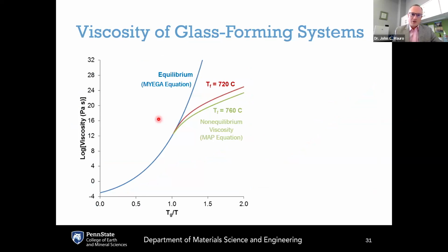Another major focus of my research has been on the viscosity of glass-forming liquids and glasses themselves. This plot shows the logarithm of viscosity as a function of inverse temperature here, where if you take a liquid and you cool it, you're moving to the right on this graph. The viscosity is increasing by orders of magnitude. So it's kind of like water here, and as you continue to cool it, it becomes like honey, and it becomes thicker and thicker, more and more viscous. And eventually it becomes so viscous that it becomes essentially frozen in. When that happens, you get this departure from the equilibrium curve, and then you get the glassy state here.